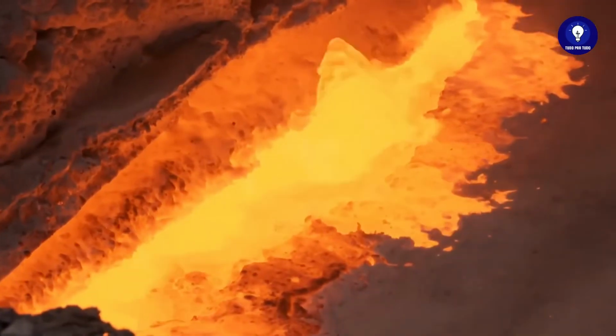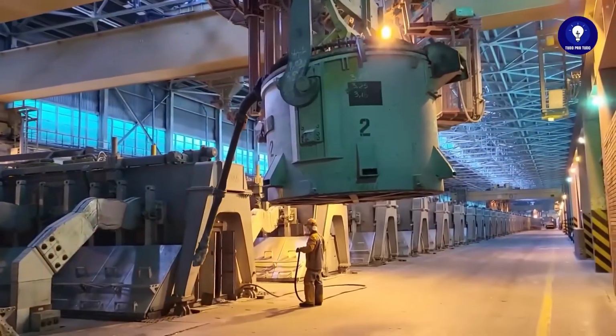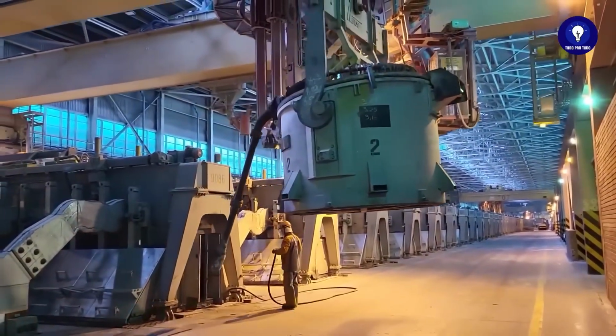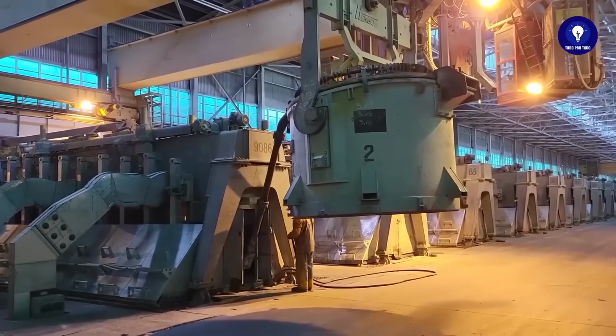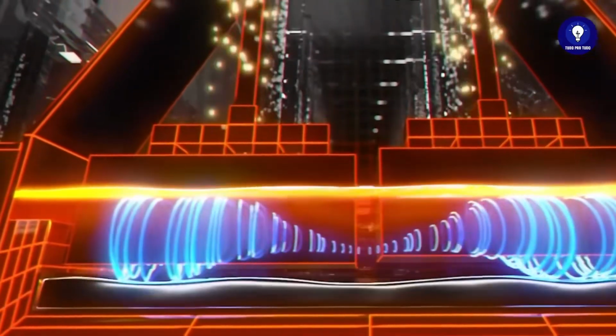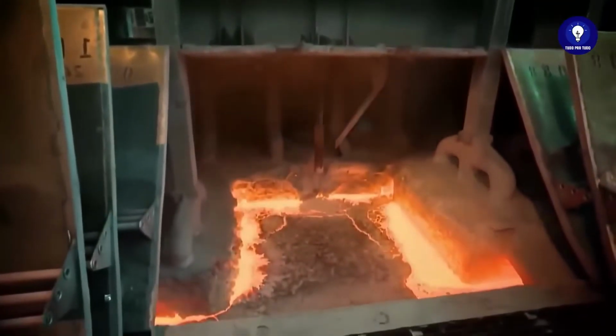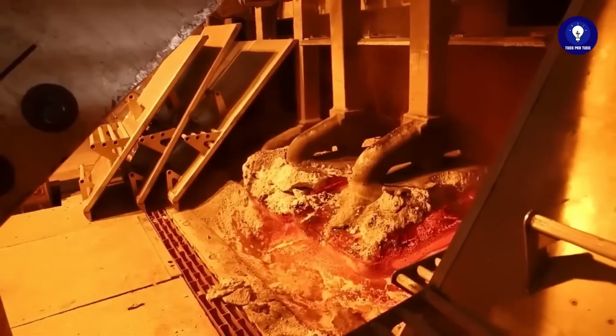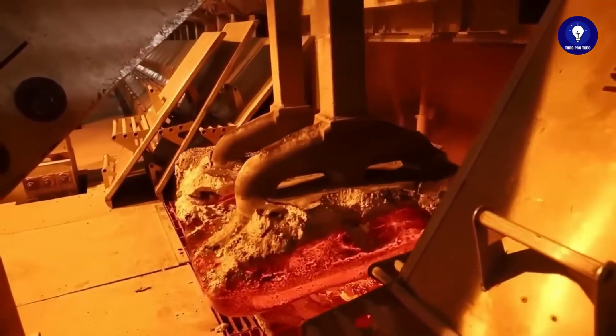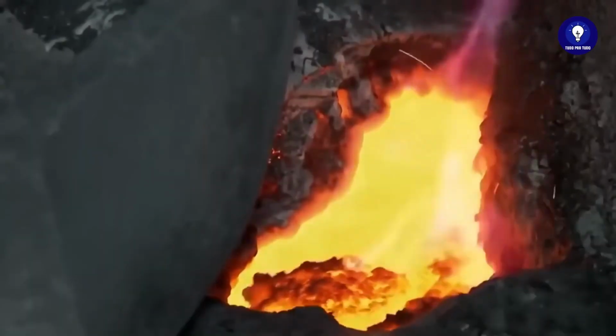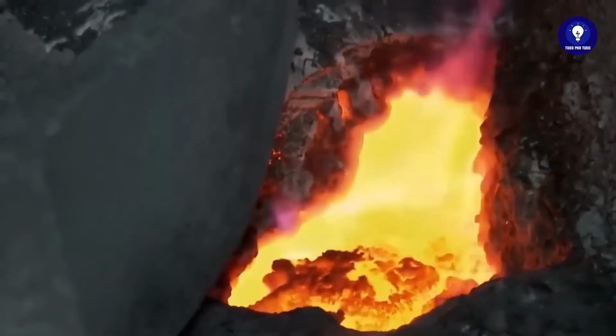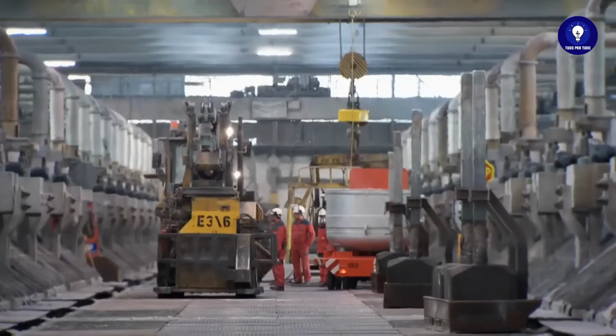The aluminum oxide molecules contained in them are made up of 2 aluminum atoms and 3 oxygen atoms. The electric current breaks these bonds, separating the atoms. The oxygen rises to the top of the container and reacts with the carbon anodes, forming carbon dioxide, while the denser aluminum sinks to the bottom of the tank. After electrolysis, the molten aluminum at about 950 degrees Celsius is separated from the cryolite by vacuum pumping. This procedure occurs in a continuous cycle every 36 hours to extract the metal from the tanks.